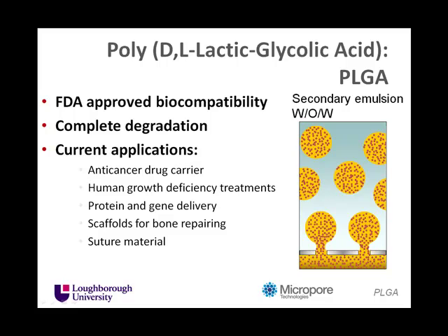We'd have leakage of the primary emulsion into the secondary water phase. Again, high shear systems, they'll give you that. They'll lead to poor encapsulation efficiencies, but this is such a gentle technique for producing emulsions, easy to control, that we can create very high encapsulation efficiencies, approaching 100%.